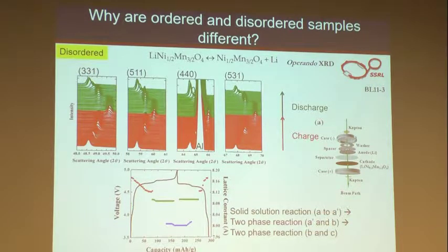So it's an interesting curve, has a lot of plateaus going on, and that tells you that there's multiple steps during this phase transformation. When you do diffraction, you see that in the initial step, your diffraction peaks are shifting constantly. This is what's known as a solid solution mechanism, until a given critical concentration where you have a second phase nucleate, and then it becomes a first order transition. You keep removing lithium and you have coexistence of two phases until the point where you don't have the first one, and then a third phase will nucleate. And then you have another first order transition that just carries you until the end of the delithiation. If you bring it back down in potential, then you get the reverse process.